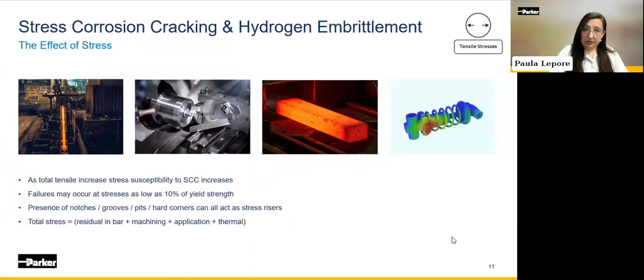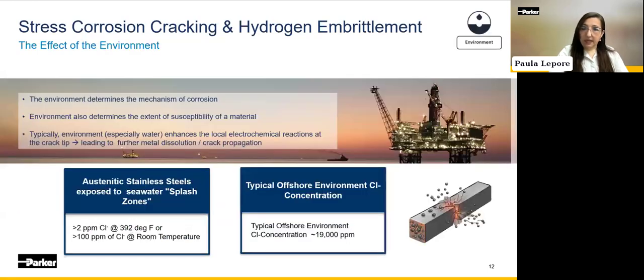So talking about the first pillar for SCC and HE to set in, tensile stresses are directly proportional to SCC and HE. Tensile stresses come from a combination of effects that the component will be subjected to during service life, from raw material forming to machining to heat treatments, cold work, assembly, installation, operation, etc. Now, the second pillar is the environment. The more corrosive the environment, the more critical the issue. The environment will ultimately dictate the corrosion mechanism. Requisites like higher temperatures and relatively high concentrations of chloride, sulfide, and H2S in wet environments are critical.